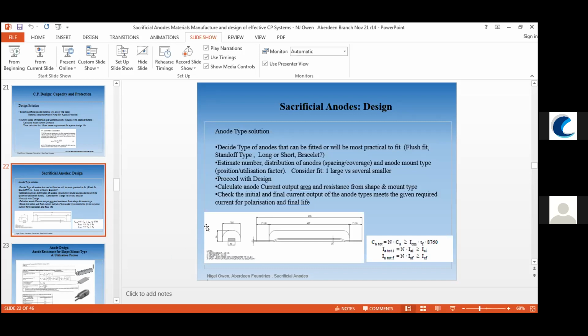And then at the end of its life, all the anode material starts to be lost from these bars, and you get down to what is known as around about 10 to 15% of the anode material left. And that is when your anodes need replacing. That is the end of life.